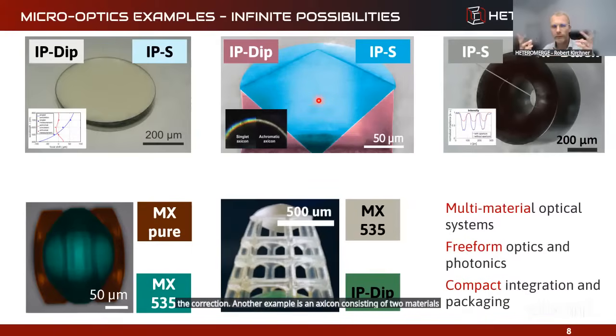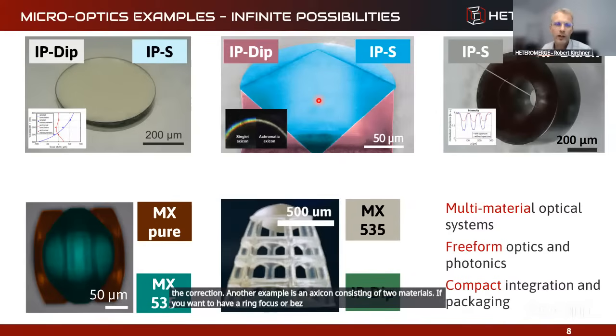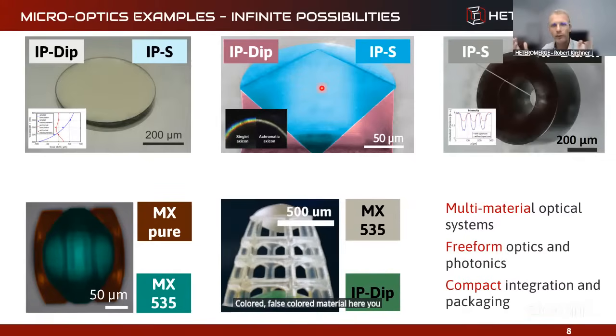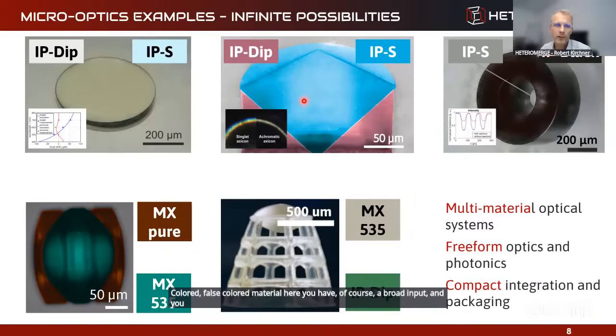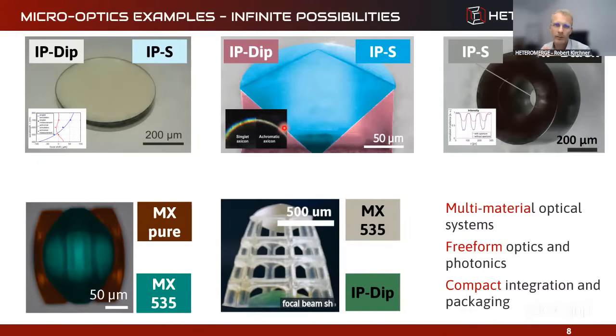If you want to have a ring focus or Bessel beam generation, where you have one single hexagon, which would be the top one, the blue, false-colored material here, you have, of course, a broad input and you get a splitting of the spectrum, obviously. And if you combine it again with the different material, but the same two you had before that are very suitable in dispersion, you get a very chromatic, corrected focal beam shaping, so to say.